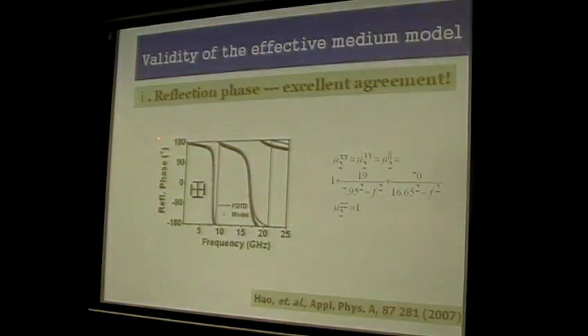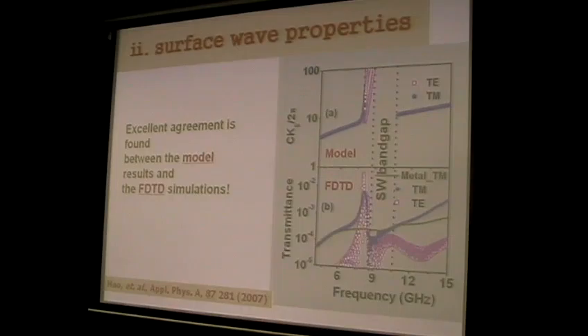And we can demonstrate this idea by considering both the reflection phase properties and also the surface wave properties. For the reflection phase properties, we found the effective medium model gives a perfect agreement with the FDTD simulation on the realistic structures. You can see the agreement is quite good. And the model can also describe very well the surface wave properties of these realistic structures.